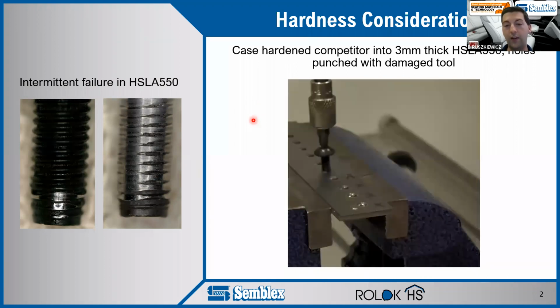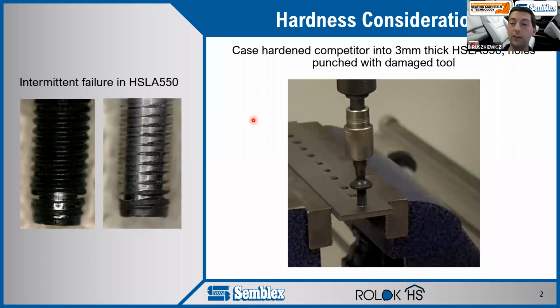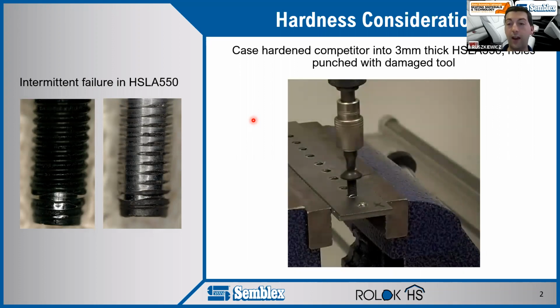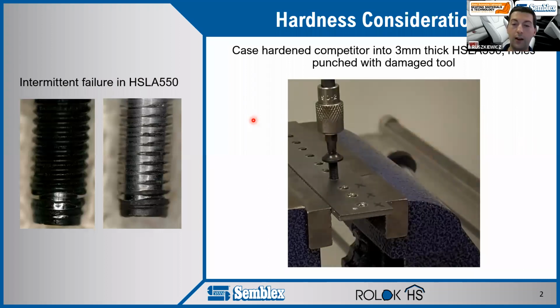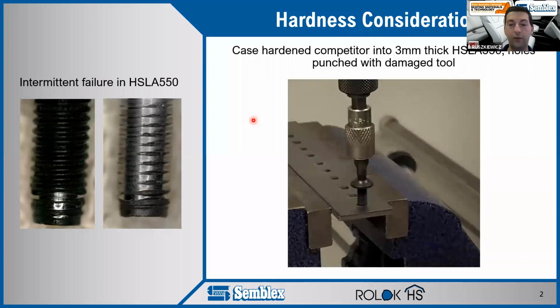Now they noticed that this failure was intermittent, and they eventually linked this back to their punch presses. So when their tooling started to wear, they started to have issues with these parts driving in. Upon some closer inspection, they found that when the tool started to wear, the interface hardness right at the edge of that hole got very high, and this caused some of the fasteners to start to deform.